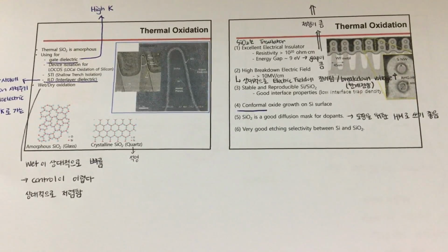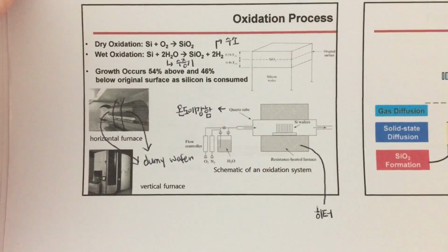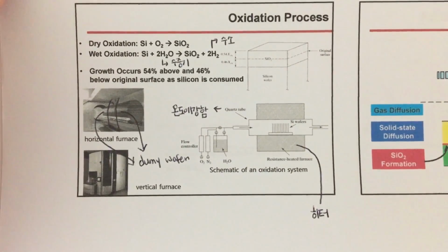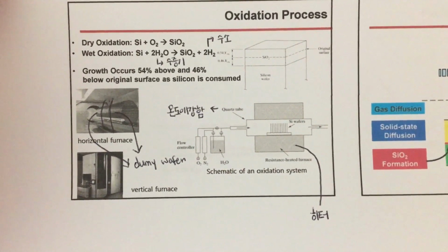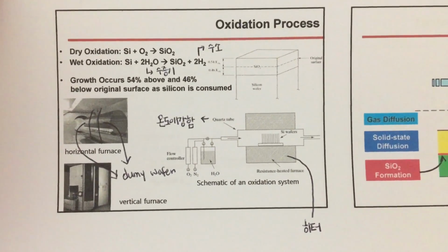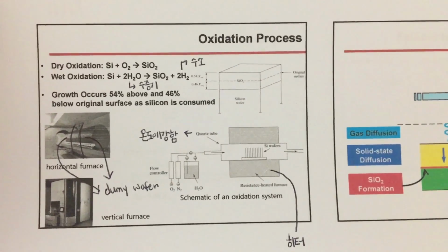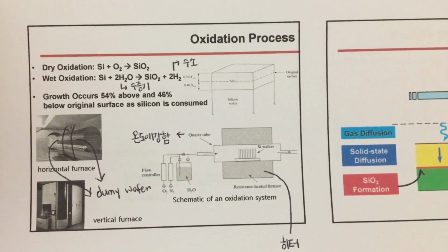silicon dioxide. Wet oxidation is preferred to dry oxidation for growing thick oxides because of the higher growth rate. Wet oxidation also yields a lower density oxide with lower dielectric strength.